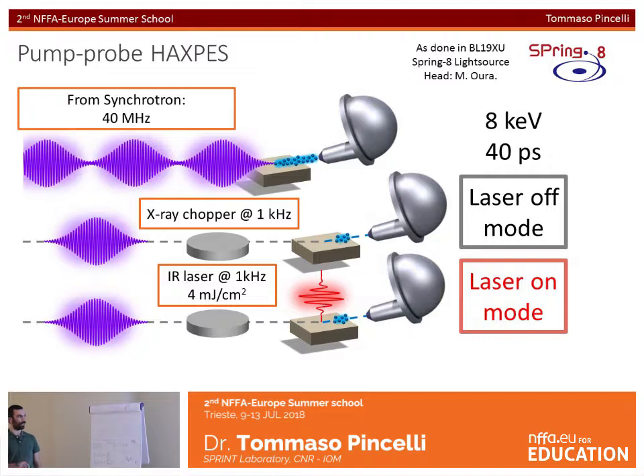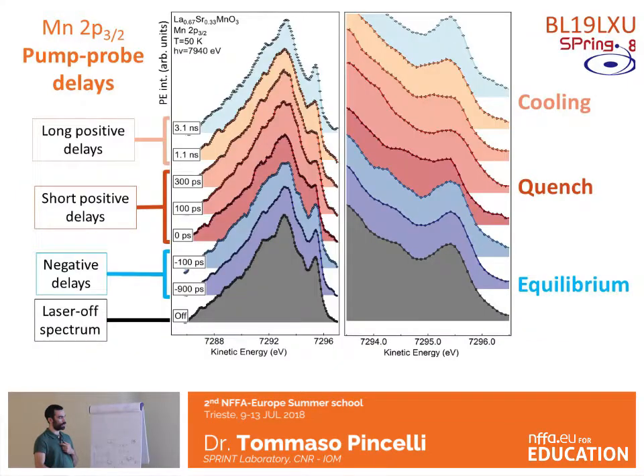And then they shine the pump laser, and they control the delay between the synchrotron pulse and the laser pulse. And if you do this on the manganese peak that I showed you before, you obtain this cascade. This is a measurement of the peak with the pump laser switched off, so that we look at the equilibrium state. Then we look at negative delay, meaning that the probe is arriving before the pump, and this is equal. The shape of the peak is identical to the one of laser off, and that allows us to say that we are not creating permanent changes by shining the laser. And then at the shortest delay, we see that this satellite is quenched, and then when the sample cools down, the peak recovers.